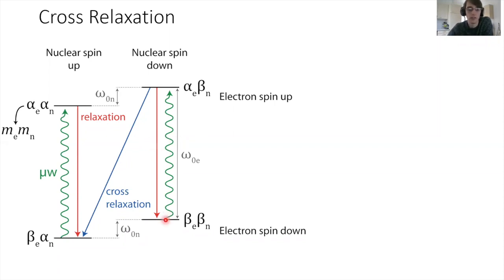And then you can see if we repeatedly irradiate with microwaves, or continuously irradiate with microwaves, we repeatedly populate these levels, and some of the time they fall down this way by a zero quantum relaxation, we're going to end up with an excess of population on this side. So we have more nuclear spins up than we would have at equilibrium, and so that's the hyperpolarization, the boost in our NMR signal.